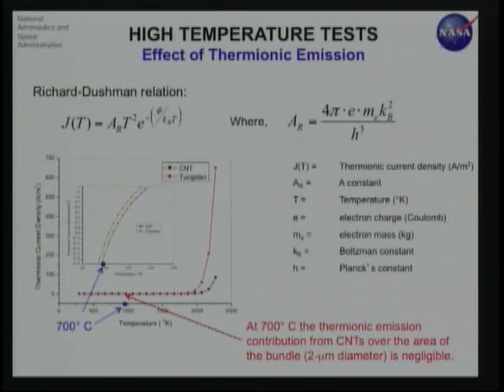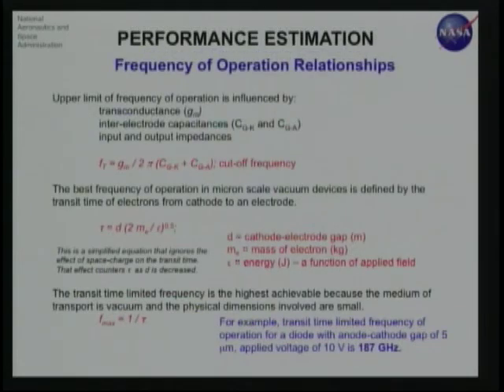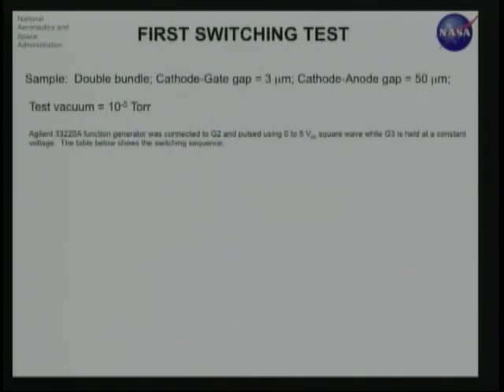Using field emission, we can make these devices operate much further. For the frequency operation relationship, we can optimize the transconductance of the device, etc. But the bottom line is, if you can control the space charge at the anode, which slows the operation of your device, then simplistically speaking, the maximum frequency of operation is only limited by the transit time of the electron from cathode to anode. However fast it goes, that's pretty much how fast the device will work, theoretically speaking. It turns out to be about 200 gigahertz or so, comparable to solid-state devices.